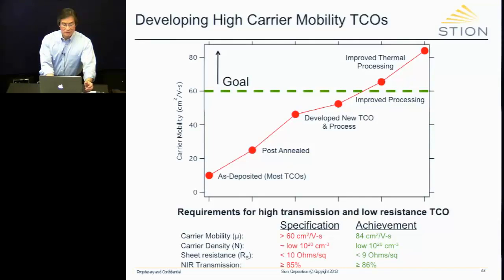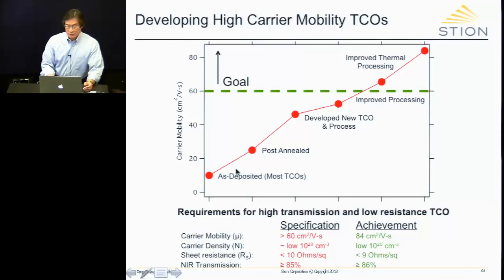In fact, I probably shouldn't even tell you this, but we would prefer that our competitors continue to use AZO for that reason. But it is a horrible TCO for that reason. Transmission suffers. So if we post anneal, on the other hand, the mobility moves up a bit. No surprise. It goes up to 20, 23 or something like that. But it will never get to the highest mobility that we need.